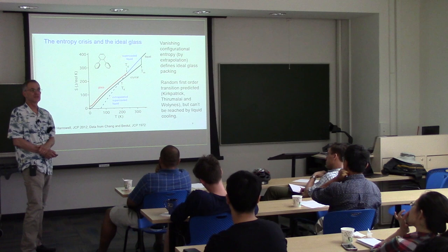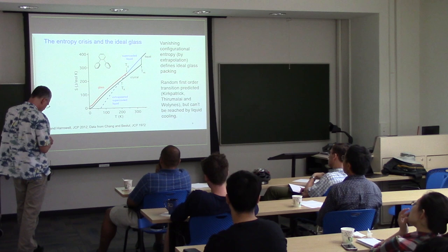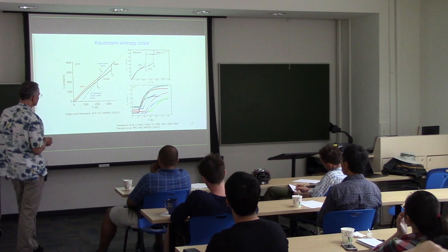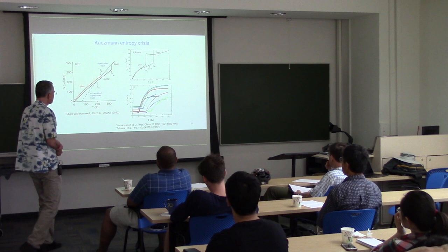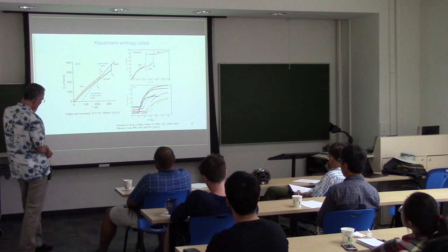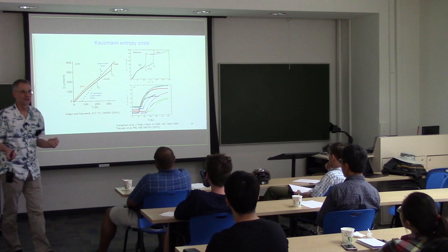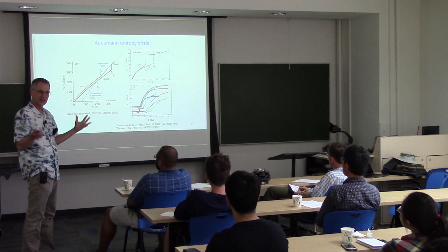And then I just wanted to focus on the panel here in the lower right. So you probably can't read this, but this is a plot of configurational entropy versus temperature for about 10 different organic liquids, okay? And if you focus on the steeply declining part, the flat part is when it goes into the glass. But if you didn't go into the glass, if you stayed in equilibrium, you see every one of those systems is headed towards the configurational entropy being zero, well above absolute zero, okay? And so this is the constraint that entropy places on what kind of amorphous systems can be prepared.